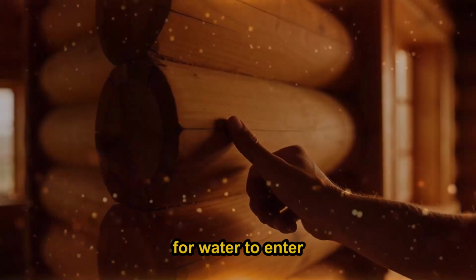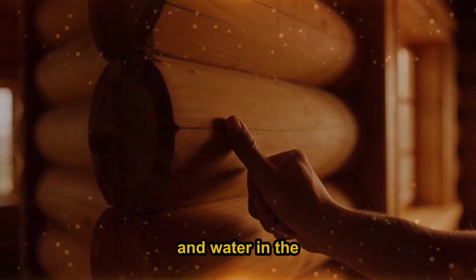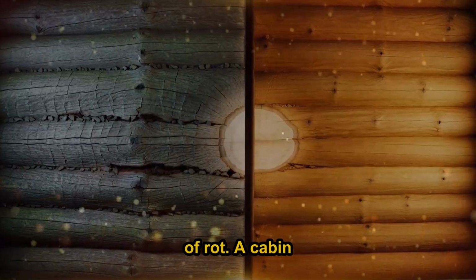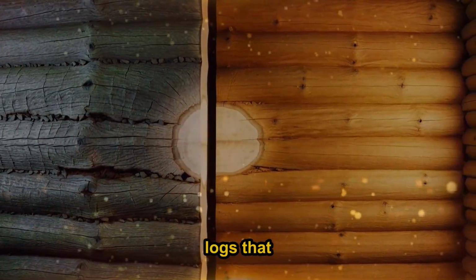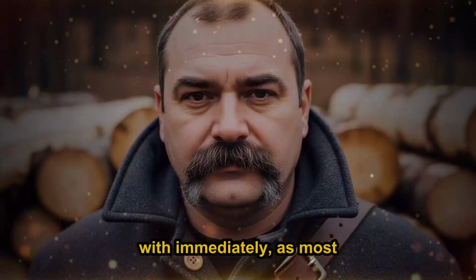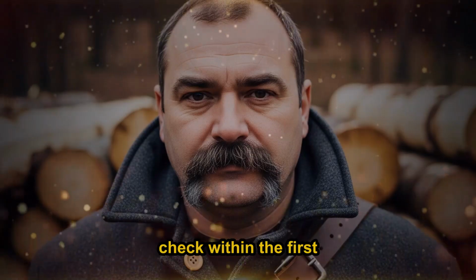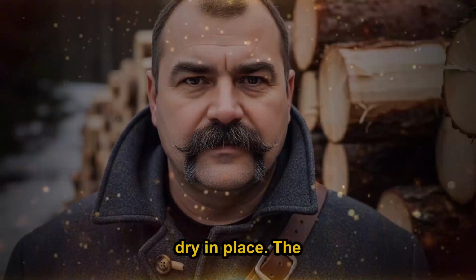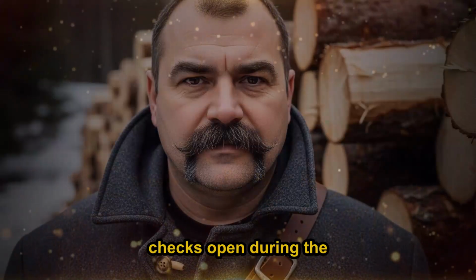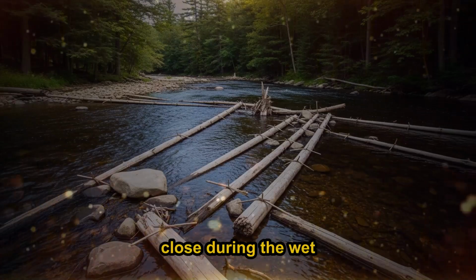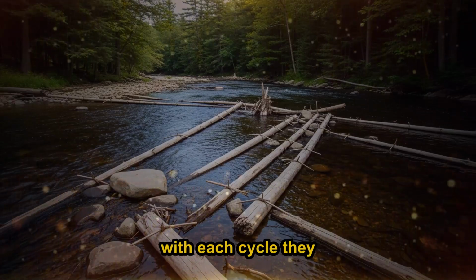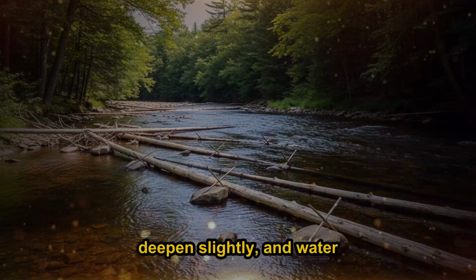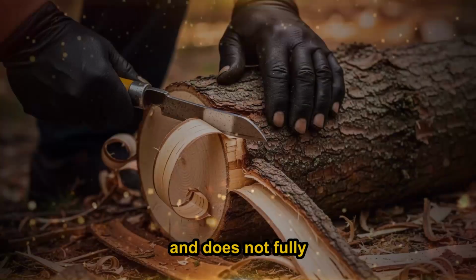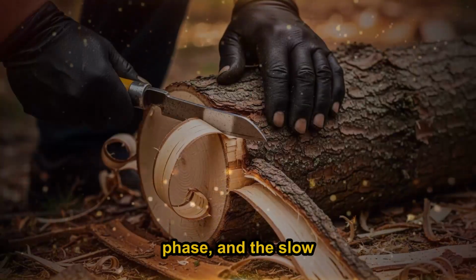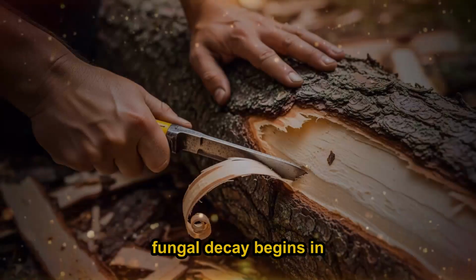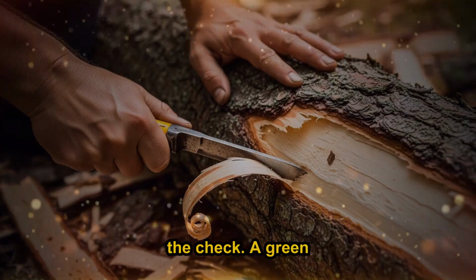Every check is a pathway for water to enter the heartwood, and water in the heartwood is the beginning of rot. A cabin built with green logs, logs that were felled and built with immediately, as most frontier cabins were, will check within the first year as the logs dry in place. The checks open during the dry months of summer and partially close during the wet months of autumn, and with each cycle they deepen slightly, and water enters during the wet phase and does not fully leave during the dry phase, and the slow process of fungal decay begins in the damp heartwood behind the check.